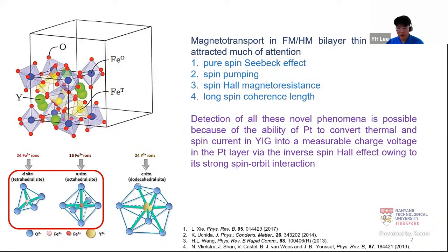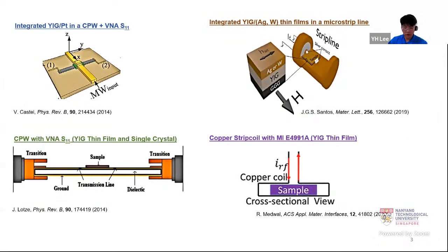And the reason why this is possible is because the platinum is able to convert thermal and spin current in YIG into measurable voltage through the use of inverse spin Hall, owing to its strong spin orbit interactions. While preparing for this project itself, I actually chanced upon many groups researching on the YIG platinum layers,